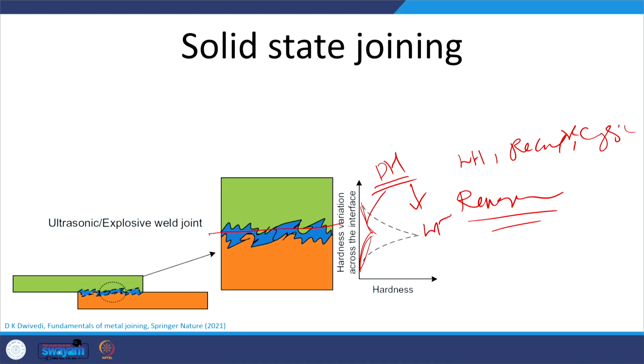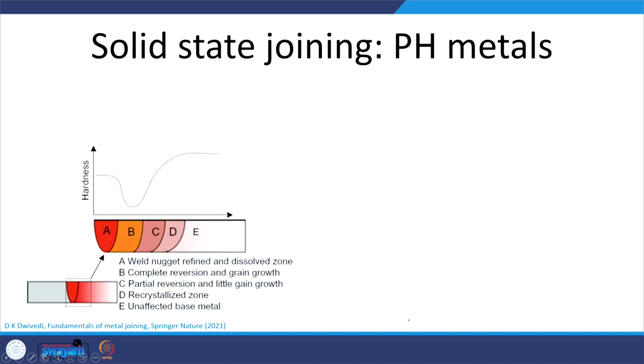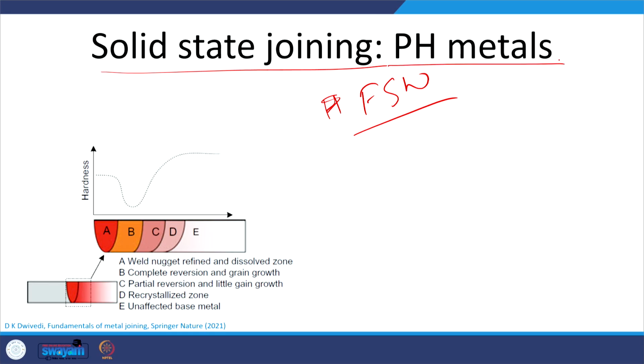So, this may be true for the work hardening metals, and the other can be true for the precipitation hardening metals. Okay. Now, if we talk of the solid state joining process where significant plastic deformation is involved, like FSW, friction stir welding, in the case of the precipitation hardening metals, these metals are strengthened by the formation of fine precipitates in the matrix.